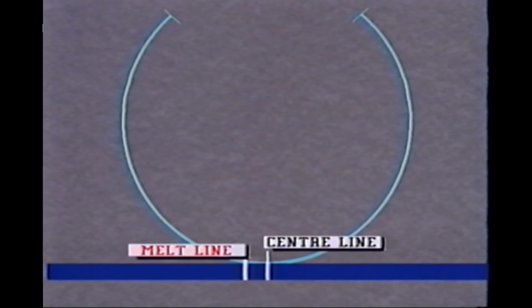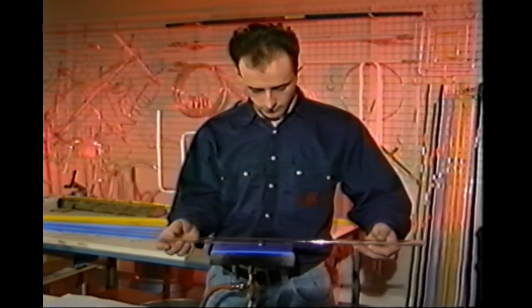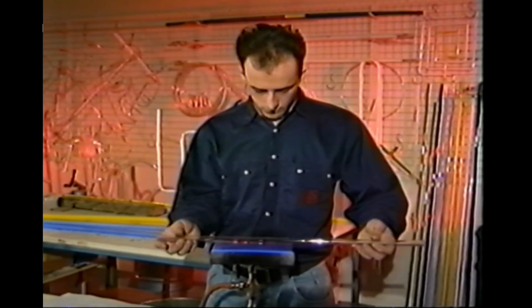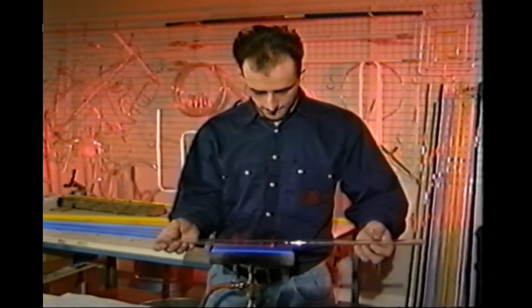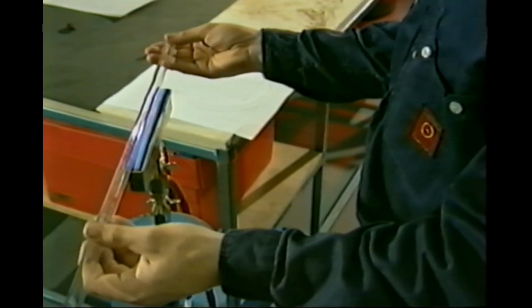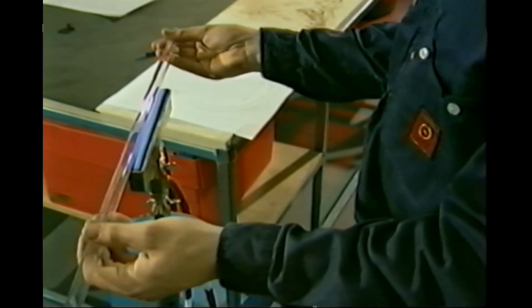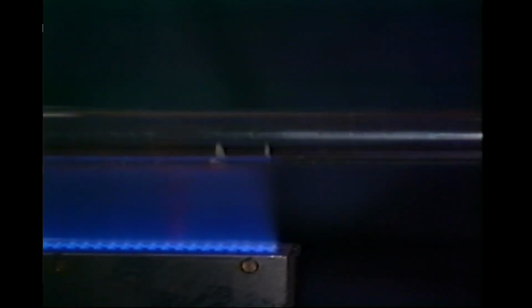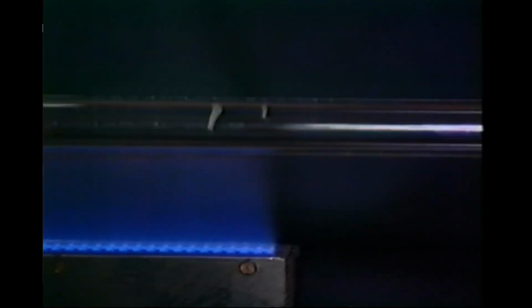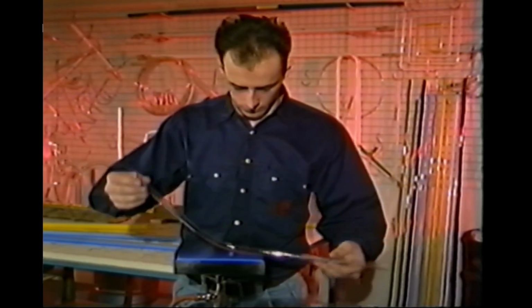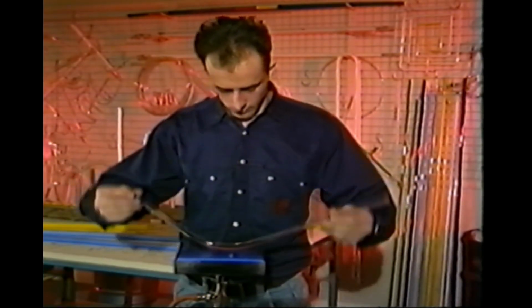Grasp the tube in both hands out towards the open ends of the length. Roll the tube forwards using all the fingers and thumbs. Melt the tube until it's very soft but not glowing red, keeping it parallel and in line with the burner head. When correct heating is achieved, cease rotation with the mark at the top. Allow the underside of the tube to melt a little longer, and at the same time raise slightly both ends to produce a gentle, even radius.